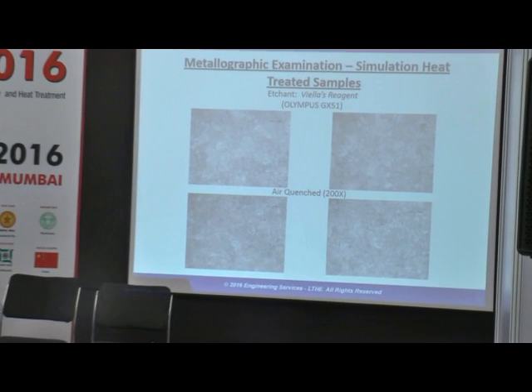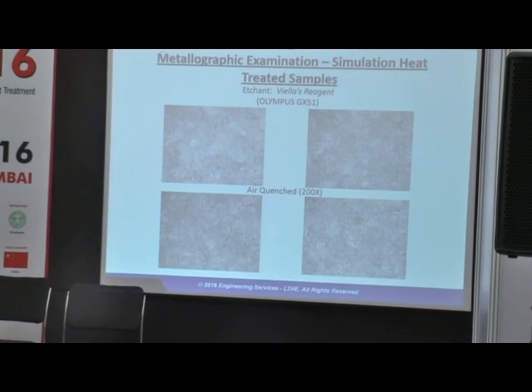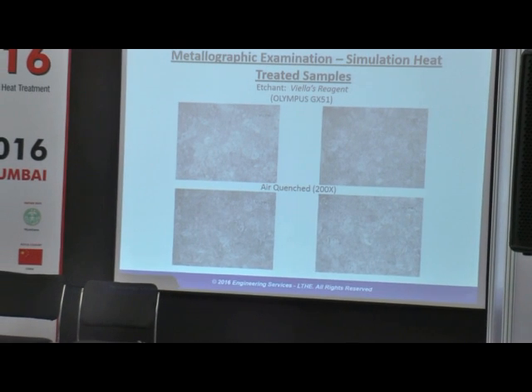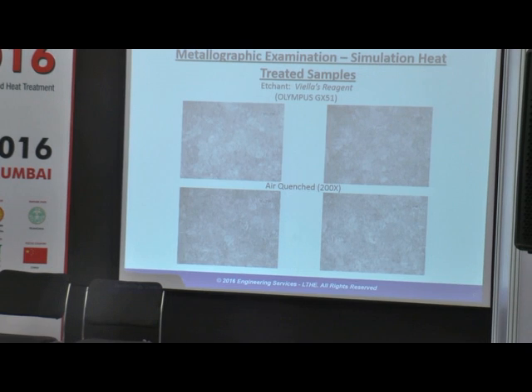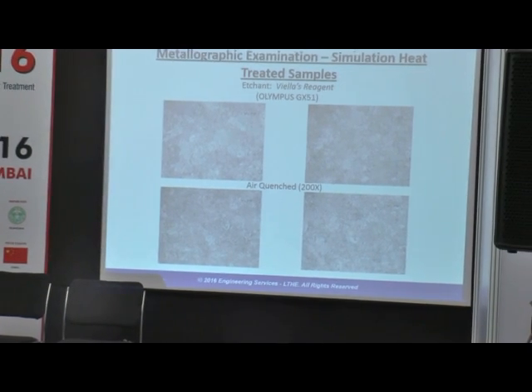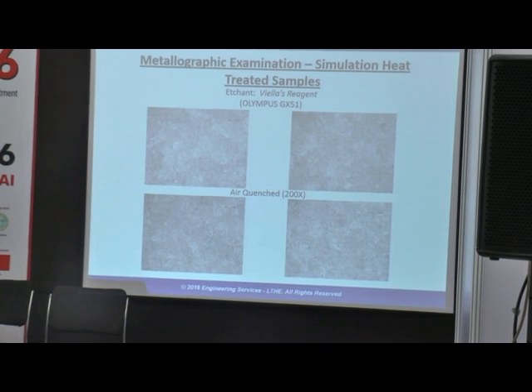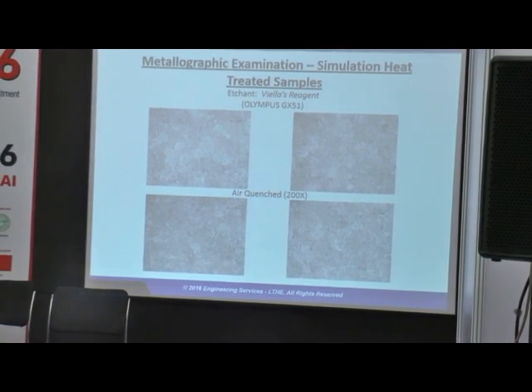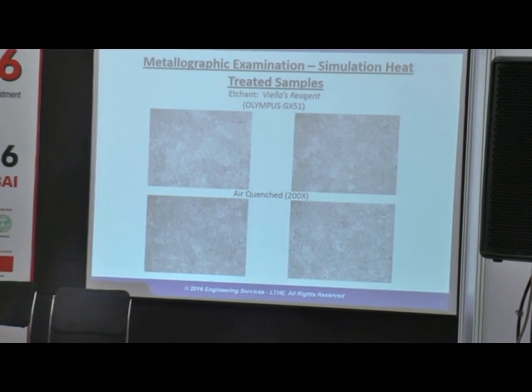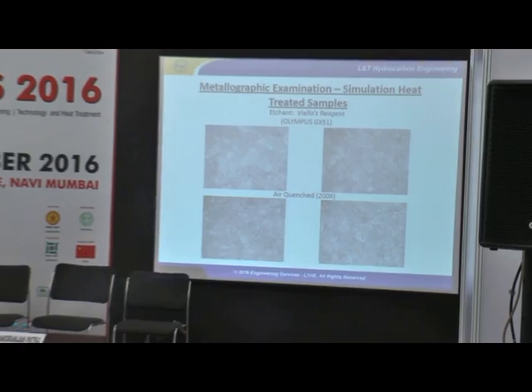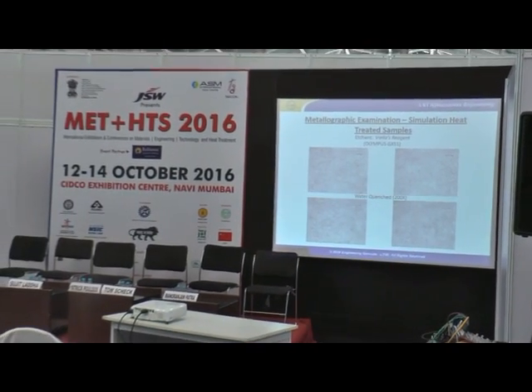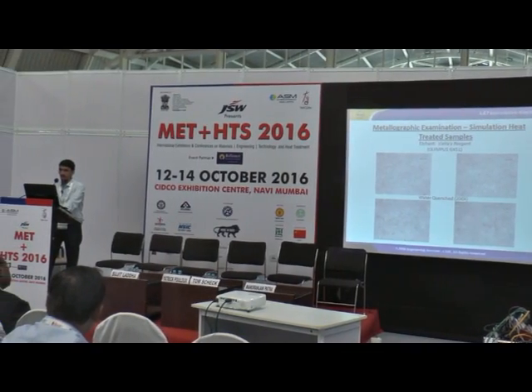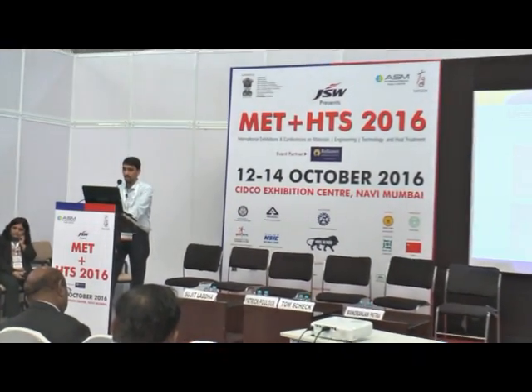Now this is the microstructure you can see for the specimen which was quenched in air. If you compare this structure with the structure in as received condition, you can clearly see that the structure now is very uniform, tempered martensite altogether, as compared to three different structures in the same component. Again, this was consistently obtained for the water quenched sample as well, a uniform microstructure of tempered martensite. So this was again one of the points that proved that the heat treatment was improper.